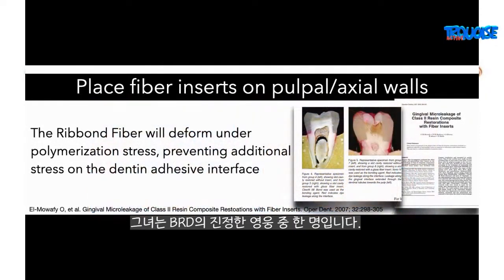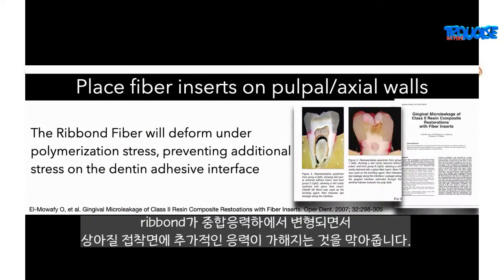But the stress reduction of the C-factor stresses that were first shown in 2006 and 2007 by Sema Belli and her team are just really monumental innovations. Just so glad that she did what she did in Japan and now continues it in Turkey. She's one of the real heroes of biomimetic restorative dentistry. And so by placing fiber inserts on a pulpal or axial wall, this ribbon fiber deforms under polymerization stresses, and it prevents additional stress on the dentin adhesive interface.